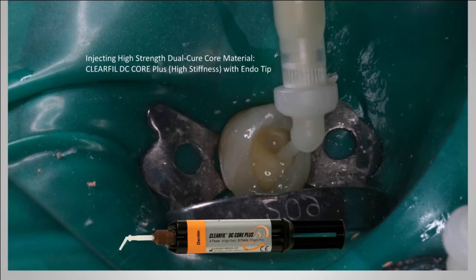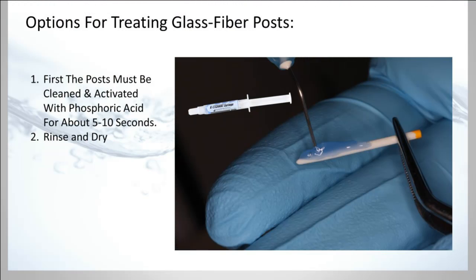And then this is the DC Core Plus, and this is the endo tip. Put that endo tip all the way to the base of that and fill it. Bring it up quite a ways. And this is what the product looks like, and this is the syringe it comes in. You just push that down in there. And then you treat your glass post with Etching Gel.